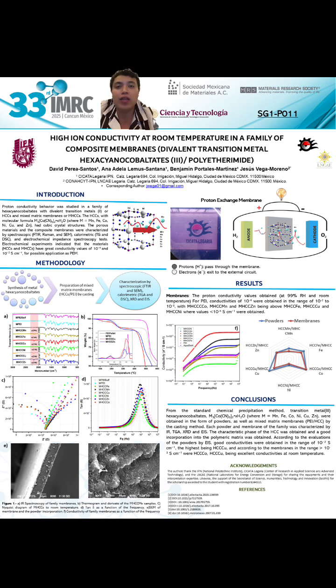Through tangent delta, we can determine the maximum frequency in both diagrams to see the coincidence of the conductivity. And likewise, through SEM micrographs, we observe the membrane composed of the hexacyanocobaltates, where we can see a homogeneous and distributed phase with grains of 1 to 2 micrometers and agglomerates of up to 3 or 4 micrometers.